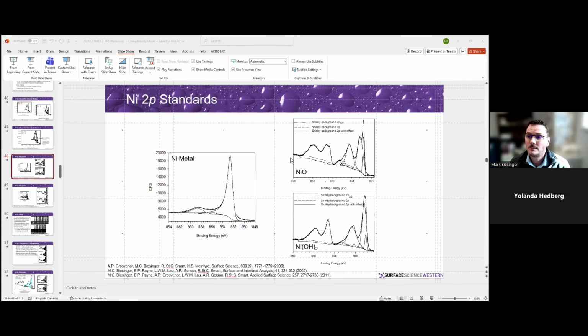For something like a nitride or a carbide, they will also have their own peak shapes, and those things have to be taken into account. And we base that again on standard samples and those sorts of things. The nitrides, I think, have some other structure going on. It's either shakeups or there's bulk plasmon. There's a bunch of other stuff going on. I have some of that on the website, so that can direct you to some good papers for titanium nitride, which will have different shapes. The carbide I think looks very similar to the metallic peak with an asymmetric peak shape. So, good question.